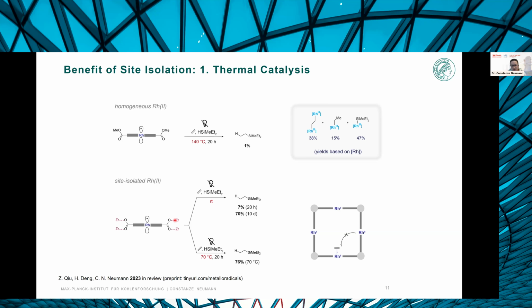And then we can carry out thermal catalysis of hydrosilylation, even at room temperature, with very slow reaction rates, but without any deactivation of the catalyst, so that over 200 turnovers can be achieved after 10 days. If we heat the reaction up somewhat, then synthetically useful yields can be achieved after a much shorter reaction time. But whereas the MOF catalyst can react efficiently at 70 degrees, when you look at the homogeneous catalyst, even at 140 degrees, less than 1% of the desired product was formed.